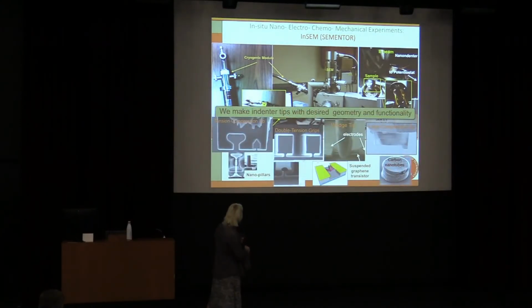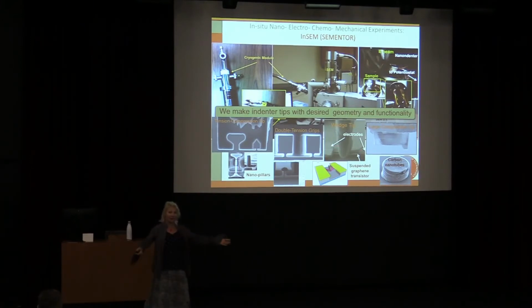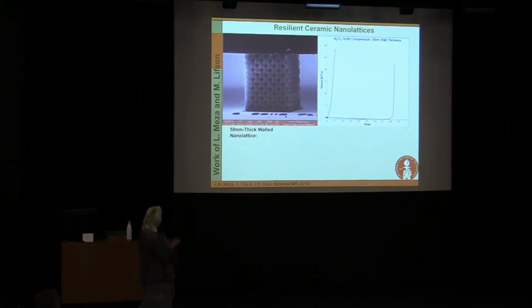So without all these bells and whistles, it would just be an SEM chamber, just a scanning electron microscope. But now we have a nano-mechanical module which allows us to use all these different indentation devices. So we can do tension, compression, we do a lot of different kinds of mechanical perturbation that allows us to study these materials and how they deform at multiple length scales. So here's a big question. This is an architecture, all made out of alumina. So how many of you have done ALD, atomic layer deposition?